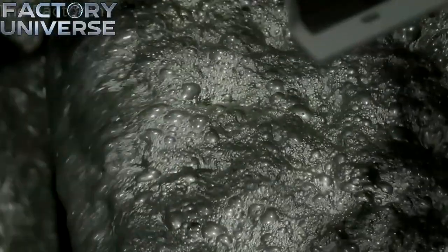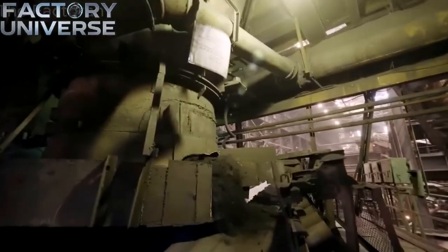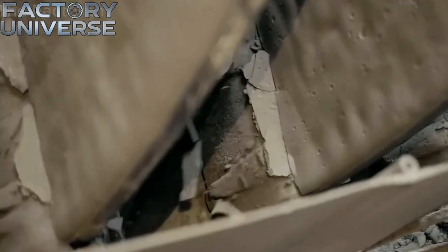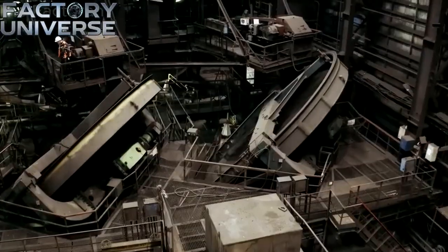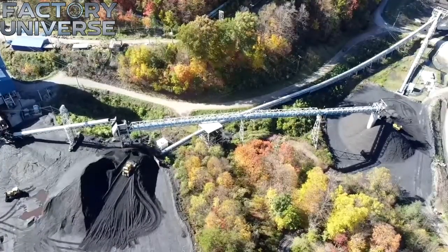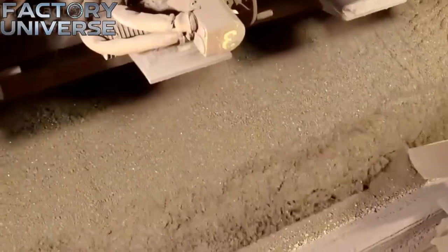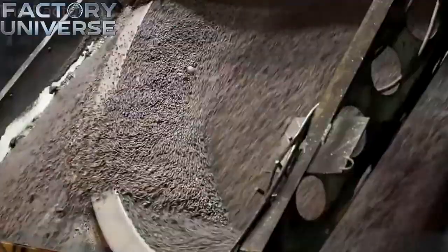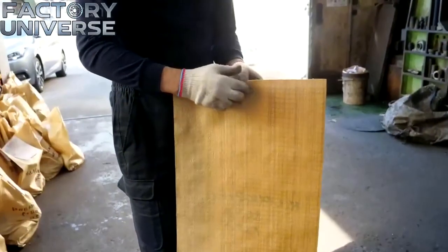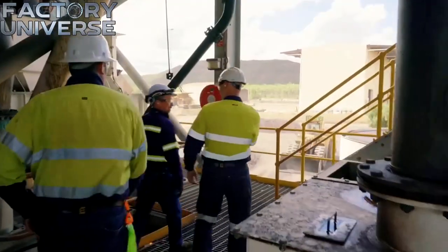This iron-rich froth is carefully skimmed off by automated manipulators and collected through multiple cycles of concentration. This refinement produces a concentrate with iron content often exceeding 65 to 67%. This is more than twice the concentration of the original raw ore. It marks a critical turning point where unshaped stone is reborn as a refined resource fully prepared for the demanding metallurgy ahead. The iron-rich slurry is then fed into vacuum filtration systems, typically drum or disc filters for dewatering.